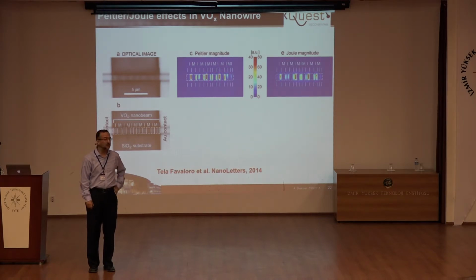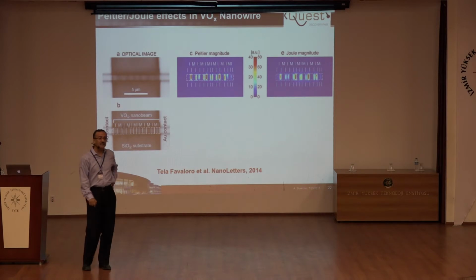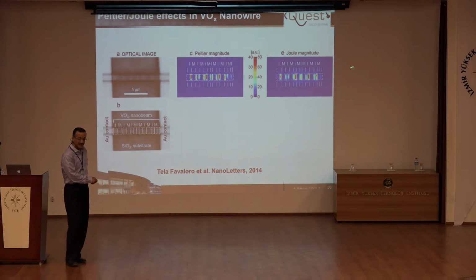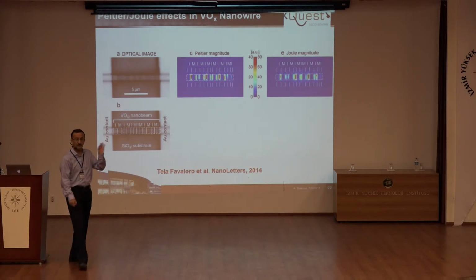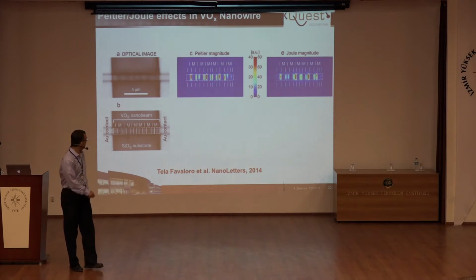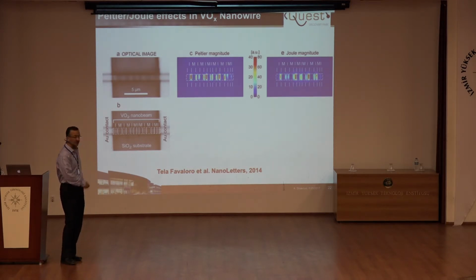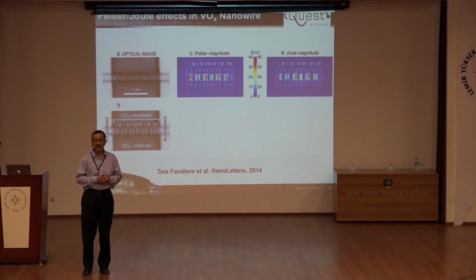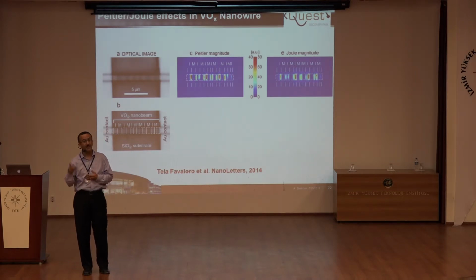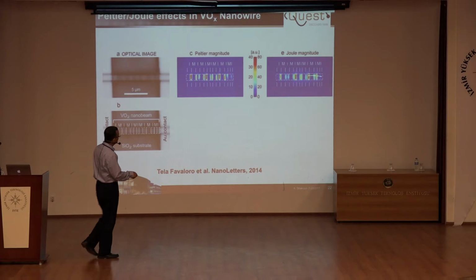Joule effect is fully irreversible. What it means is that if the current goes from right to left or left to right, you should measure the same amount of heating. So heating is proportional to the current squared, resistance times current squared. I can separate that: if the current is modulated at frequency omega, and I look at 2 omega, I only measure Joule heating. But at the interface, when electrons go from metal to semiconductor, there is a change in the average energy of the electron gas. That's Peltier cooling or Peltier heating. That's reversible heat exchange, and that way, you can see some temperature changes.